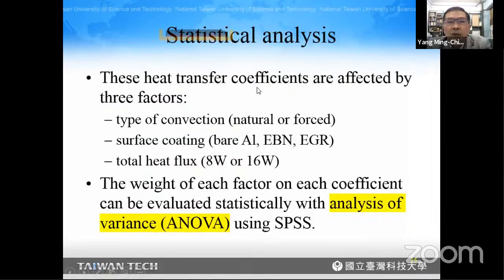Heat transfer coefficients are affected by three factors. The type of convection, either natural or forced convection. The other factor is surface coating: either aluminum, epoxy coating containing boron nitride, or epoxy coating containing graphene. And also total heat flux, either 8 watts or 16 watts. The weight of each factor on each coefficient can be evaluated statistically with analysis of variance using SPSS.